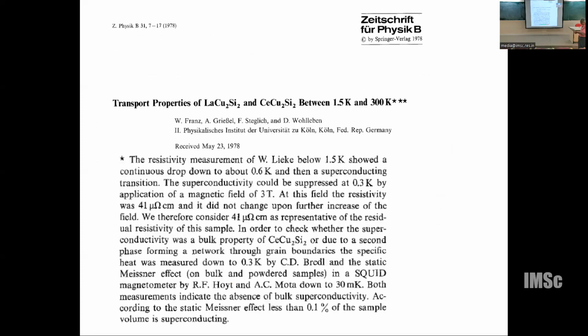Okay, there is an interesting history. Unfortunately, I don't have time. He was with Wohlleben before. He was studying a polycrystalline material. He found superconductivity at 0.3, in some samples, again not in all samples. The Meissner fraction, which I don't know in detail, the fraction of the superconducting sample, was something like less than 1%, 0.1%. He found that. And Wohlleben, being the boss, did not want to make it a part of the paper: what do you mean, some samples show?